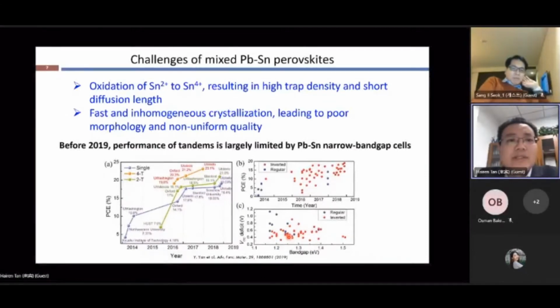The first is the easy oxidation of the tin 2+ ions, and this will result in a very high trap density and short diffusion length in the resulting perovskite films. And also, due to the introduction of the tin ions in this precursor solution, usually the perovskite film crystallization becomes very fast and inhomogeneous. And this usually leads to poor morphology or non-uniform electronic qualities in the films. So before the year of 2019, the performance of the tandem devices actually was largely limited by the mixed lead-tin-based narrow bandgap perovskite solar cells and materials.